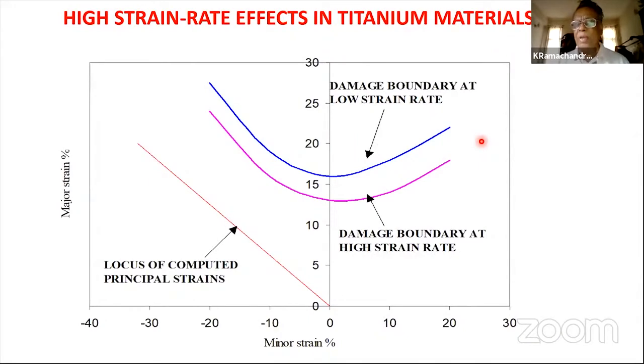But this is dependent on our ability to understand the high strain rate behavior of the material. They are not the same as what we get from a simple tension test, and that's at a very low strain rate. High strain rate could be as high as 2,000 to 5,000 strains per second, and the behavior of this material, of the titanium, for example, at the front of the engine, is so much dependent on the strain rate.